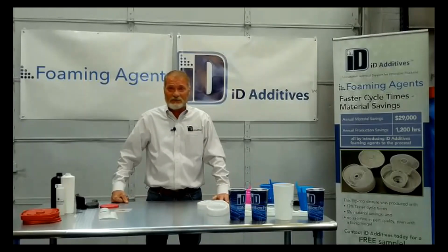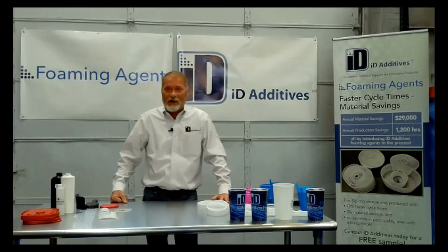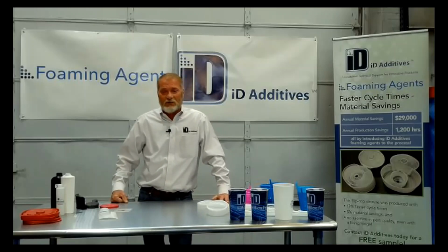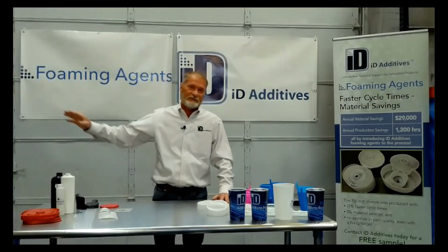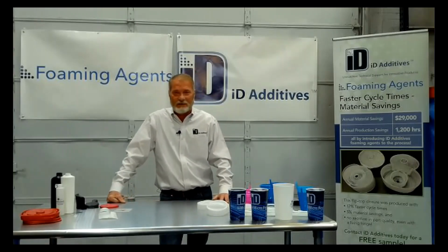Very tight cell structure. A lot of styrenes are vented. So when you're doing extrusion on parts, a lot of post-consumer, they dry it, things like that, or they have vents in their barrel. I do not recommend vents. You need to close them up, because if you have a vent, that foaming agent, it's gone. It'll go right out the vent and you won't have anything. So vents are really important when it comes to extrusion. Got to cap them off.